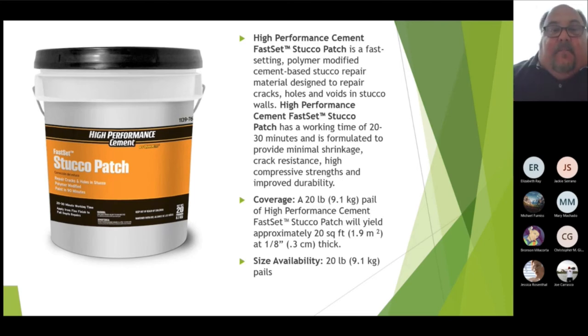Everybody, a lot of questions about coverage. It's really, really simple, and I'll show you a way to cheat. If you have a product that doesn't have aggregate in it, let's say you have this 20-pound pail right here of a stucco patch. If there's no aggregate in it, you take the weight of the pail, which is 20 pounds, divide it in half, which is 10, and that's how many square feet it'll do at a 1/4 inch. It's really simple. If somebody asks how many bags do I need in a sand topping mix, it's a 60-pound bag. Well, it'll do 30 square feet at a 1/4 inch. So you can almost hit it every time like that, and it's super simple.